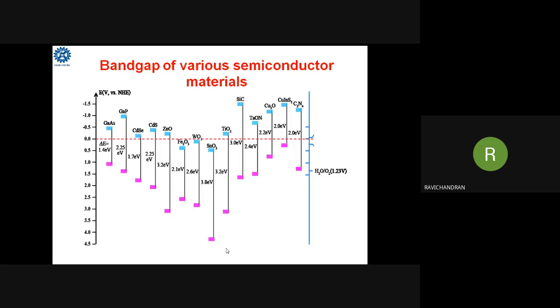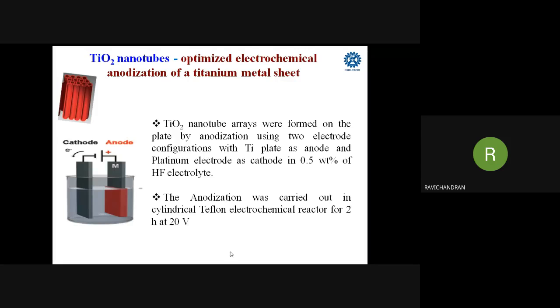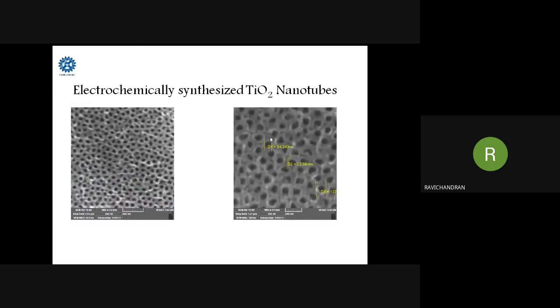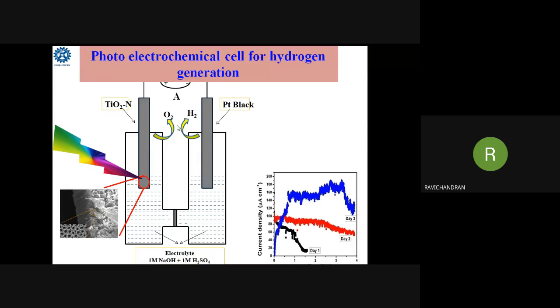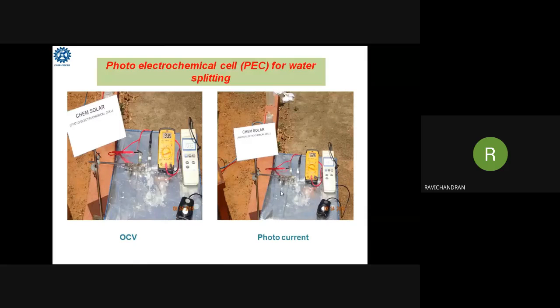So in our lab, we did some work on this TiO2 to reduce the band gap. We prepared titanium dioxide nanotubes of almost 100 nanometer, and doped them with nitrogen. The material is black on the other side. We did the photo water splitting experiment outside in natural sunlight. Instead of using simulated sunlight, we wanted a real system to observe the solar light and how much is generated.